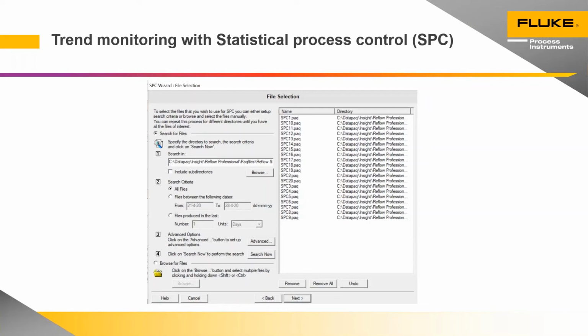Before we look at this, one thing just to say, if you're using a golden board to obtain this information, be very careful because you may end up measuring degradation in the golden board rather than changes in your oven settings. So before you start any statistical or trend monitoring, make sure that your measuring system is stable. The measurements have to be repeatable before you can do any analysis.